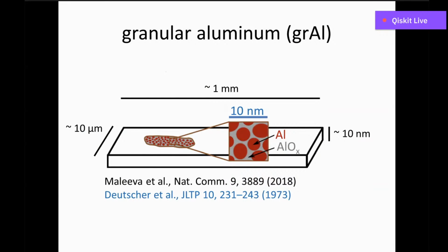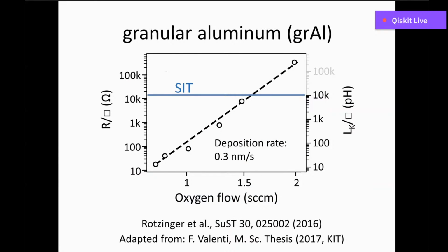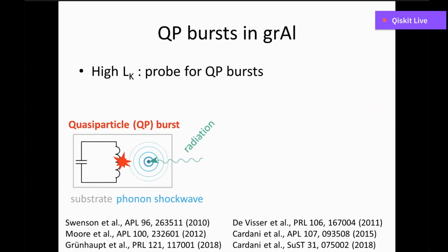This is because for a given common geometry choice that is very thin and long circuits, this microstructure of superconducting islands separated by oxide can be interpreted and modeled as a chain of Josephson junctions. Thus, if we are able to change the oxide thickness between grains, we can change the coupling of this Josephson junction chain. I show here on the x-axis the oxygen flow that is operated when depositing granular aluminum, and we see that this relates to a tunable normal state resistivity, which is then related to the kinetic inductance when in the superconducting state. And the kinetic inductance is a tool that will allow granular aluminum to be used as a probe for radioactivity. And this is how.